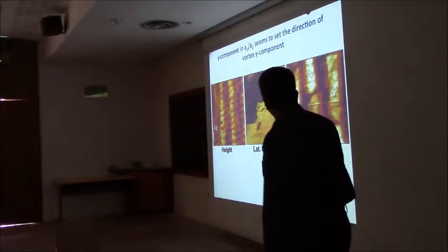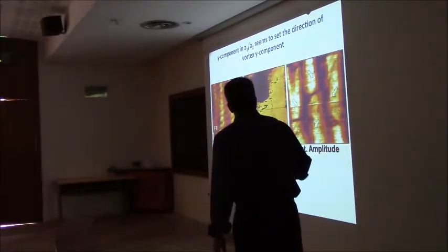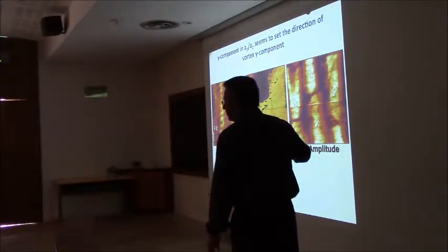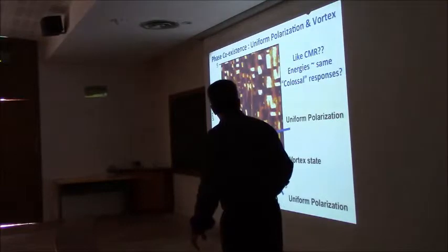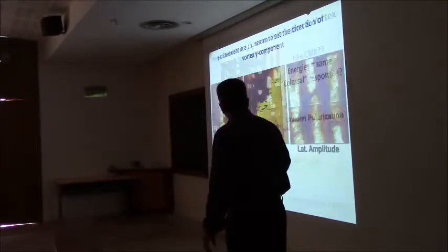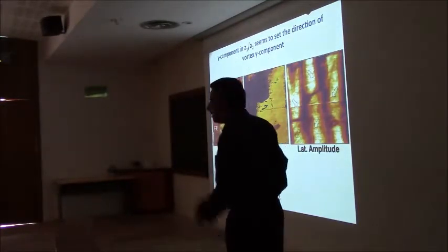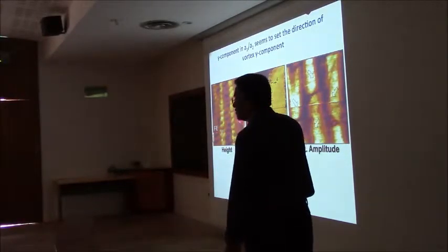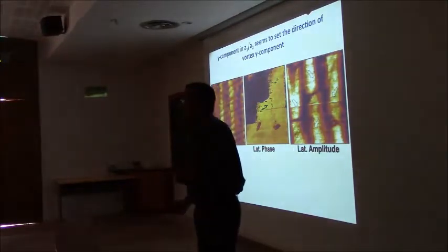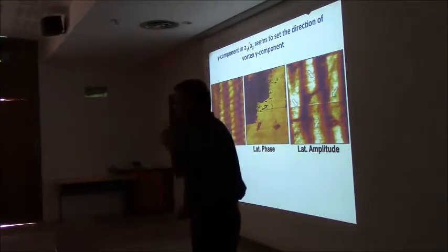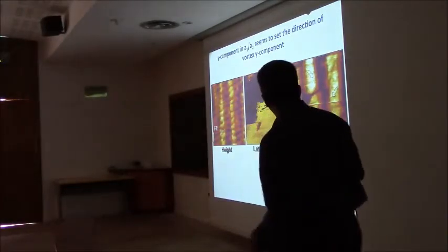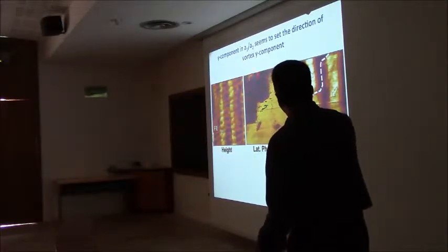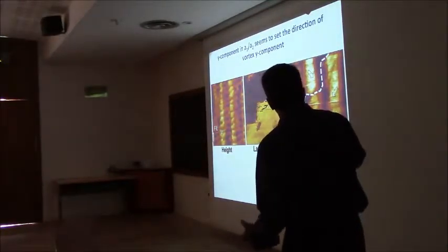Okay. I can look at the piezo response, the phase of the in-plane response, and the amplitude. And you can see that there are domain walls in the ferroelectric phase. Not a big deal. That's why you see this contrast between black and white. But what we also saw was something which was mind-blowing in my mind, that this contrast was going right through the vortex phase. And so there were domain walls in the vortex phase as well that we had not expected. So you can now say, hey, let me draw this boundary. That's the difference between a phase difference of approximately 180 degrees, and these are going right through.